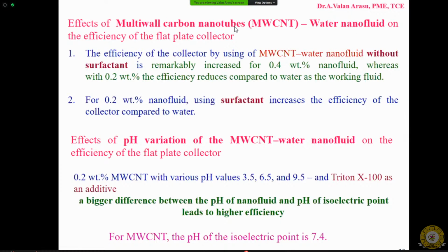Then another nanofluid, multi-walled carbon nanotube water, is used, again for different concentrations like 0.4 and 0.2. But for this nanofluid, the increase in efficiency is higher for the 0.4 percentage nanofluid. The 0.2 percentage reduces the efficiency compared to water. So we have to ensure that adding nanoparticles does not necessarily improve the heat transfer rate, because adding any solid material to any heat transfer surface will increase the thermal resistance. Similarly, adding nanoparticles does not warrant any increase in heat transfer rate.